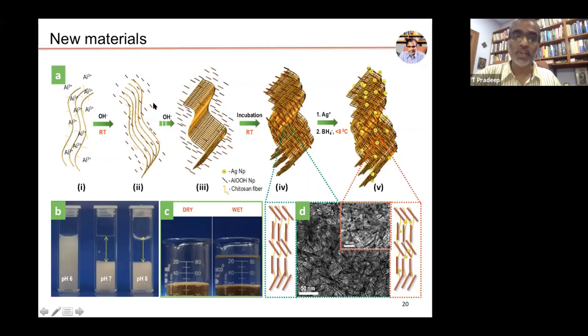So we showed that with soluble ingredients, you can make insoluble composite materials in which nanoparticles are embedded. You get insoluble, granular powders, and it is important to make granular powders because water will not have resistance to flow. You can't make nano powders and pass water through that without resistance. So these materials are made at room temperature and they are stable in water. Over 1, 2, 3 years, they are stable in water.